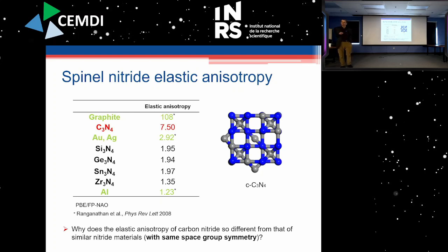A very interesting feature that we noted for these materials is you can see that the elastic anisotropy of carbon nitride is much higher than that of all of the other metal or group 14 nitrides by a factor of 4 or so. But it's also much higher than what it is for a pure metal, which is fairly anisotropic. And so we really wondered why carbon nitride has such a high elastic anisotropy compared to the other group 14 analogs, especially because those have the same space group symmetry.